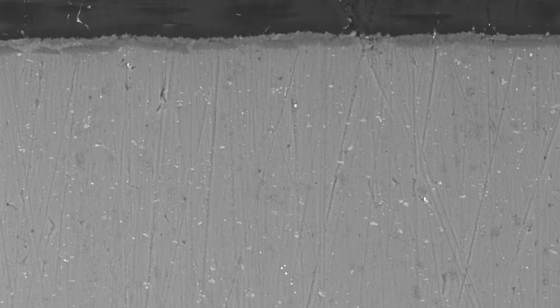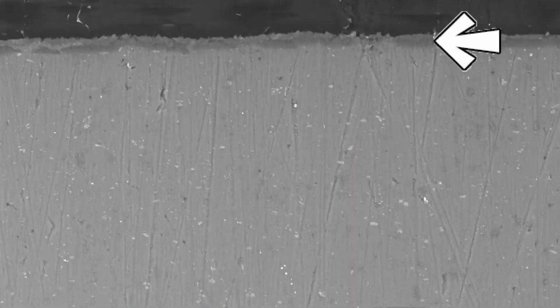Doing some analysis, we can see this lighter area here is about 99% aluminum with about 0.5% of magnesium. You almost never see anything that's made out of pure aluminum because it's so soft, it's pretty much unusable for anything. At least a tiny bit of magnesium is almost always present to give the aluminum some added strength. But in this layer on the surface, we see a ton of oxygen and a little bit of sulfur.